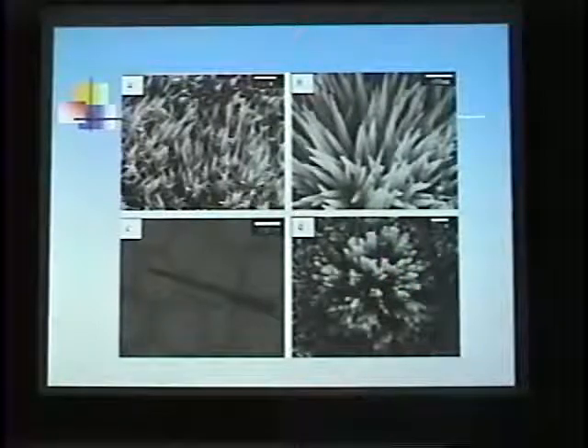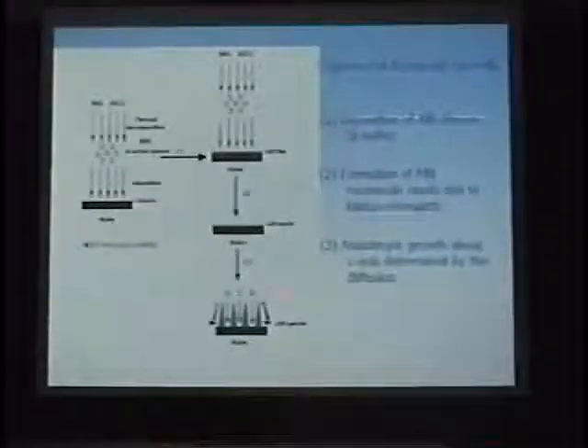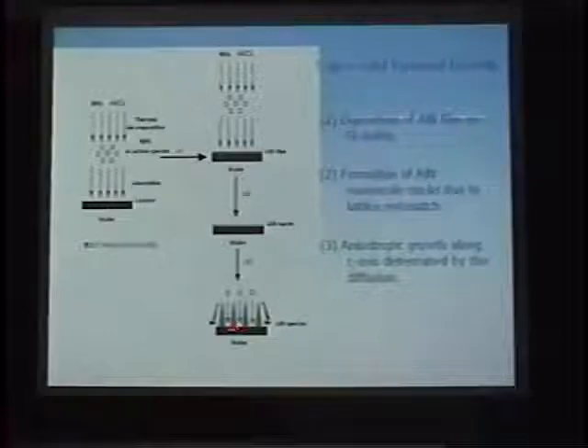And actually we have a discussion about the growth mechanism. Since the aluminum nitride species was formed in the catalyst, and it diffused in this direction with different concentration. On the upside the concentration of aluminum species will be small, and on the downside, at the bottom, the aluminum species have large concentration, so it will form such a cone structure. And when increasing the temperature, the concentration difference in this direction is reduced, so it will transform to nanocylinders. This is our explanation about the mechanism.